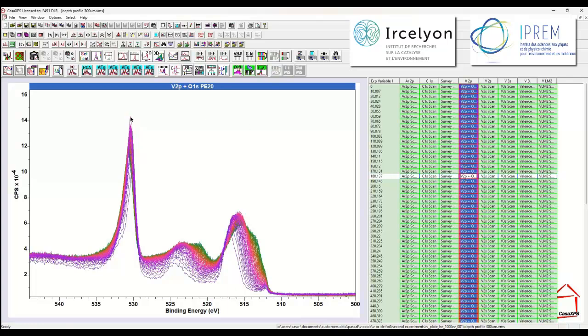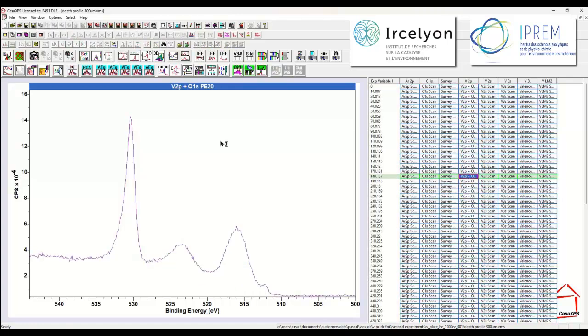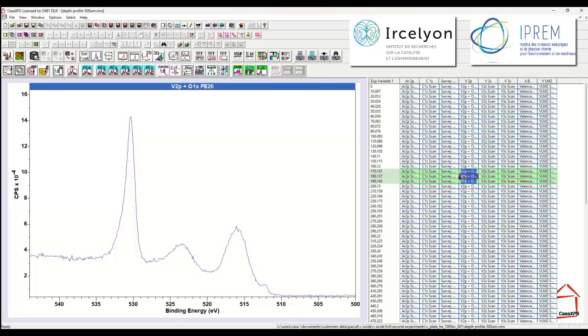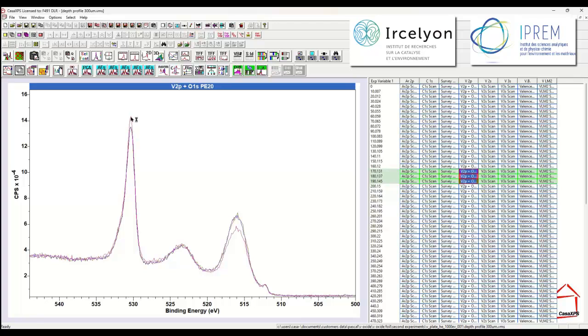And what that did was it deselected from the list of selected VAMAS blocks the VAMAS block that contains the data that we see here with the anomalous oxygen 1S. Let me display that data, and there it is. So what does that look like relative to the two spectra in the sequence of edge cycles in this experiment? If I overlay these, I can see from the colors that it's the red spectrum that is the one that is the outlier, and there really is something wrong about this spectrum, that the oxygen 1S is higher. The vanadium 2P1 half peak looks about right, but the vanadium 2P3 half peak certainly looks incorrect. And then we return to the metallic peak, and that looks correct.